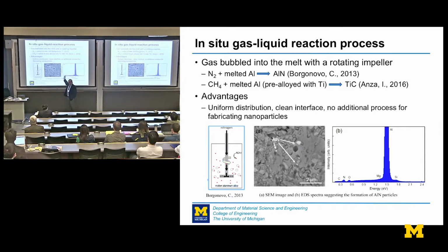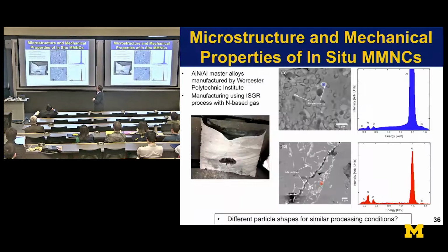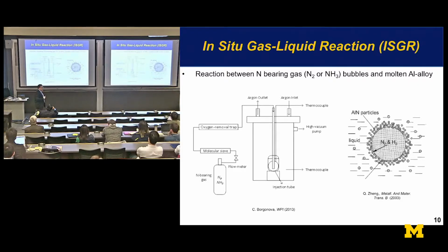We have the role of characterizing both the microstructure and the properties there. You can see we do form aluminum nitride particles. The thing is, now we're trying to scale it up. And one of the things that Jun Liu and Caleb Reese, who are postdoc and graduate student on this, found very recently is the same operating conditions, at least we believe they're the same operating conditions, and we get nicely spherical particles in one case, and all of a sudden we're getting acicular plates for basically the same conditions. And so we started an activity here, working with Professor Shahani and Rachel Goldman.